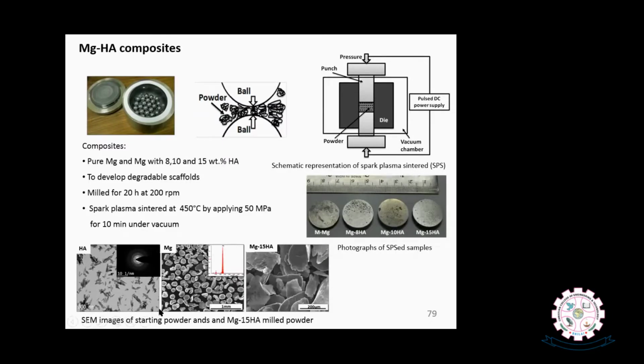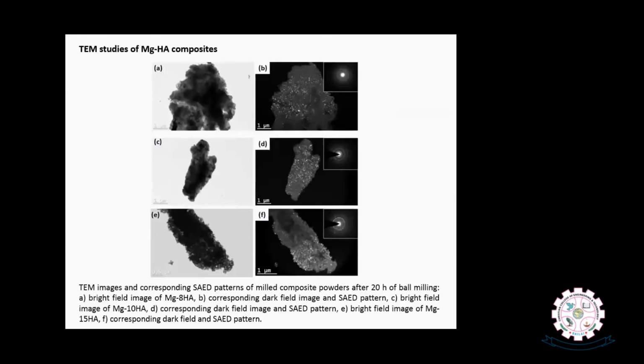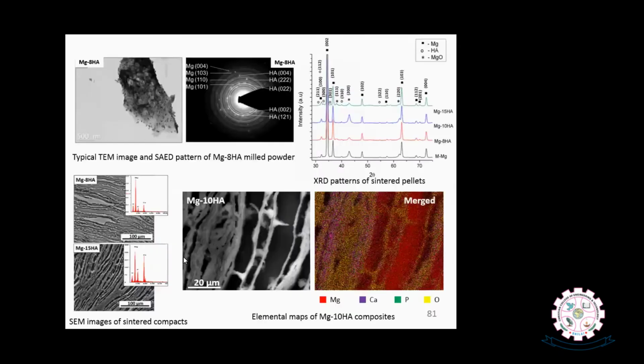You can see the SEM images and TEM images of the hydroxyapatite powder that was dispersed in magnesium powder, and also after ball milling, the morphology of the magnesium particles, which have transformed into thin flakes in these images. The corresponding TEM image also shows us the good distribution of HA crystals on the magnesium particles, as shown here in the bright field as well as, more clearly, in the dark field images after 20 hours of ball milling of magnesium hydroxyapatite powder. And here a typical single particle of magnesium coated with hydroxyapatite crystals can be clearly observed. That was observed after ball milling.